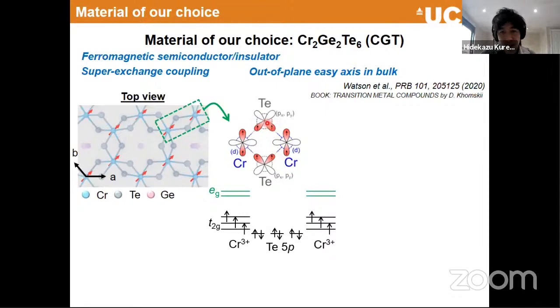And because of this orbital nature, orbital symmetry, if you try to couple this t2g state to this tellurium p state, for example, elongated along the x direction, it is impossible to couple, but still we can have a finite coupling along the y direction, but that's pretty much weak, normally. But then the driving mechanism of exchange interaction is actually interesting.